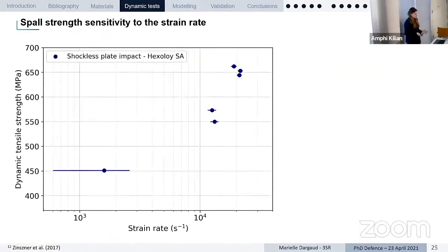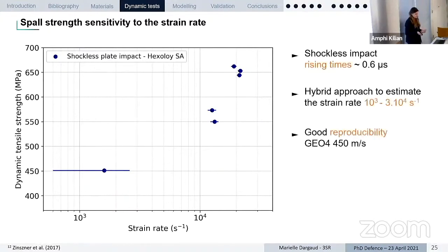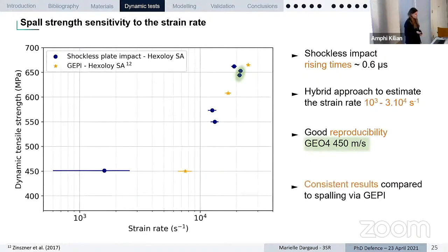From all these results, we can get to this plot where each point is just one single experiment. So here you have, for the material Hexoloy SA, the evolution of the dynamic strength according to the strain rate. You can see that we have a sensitivity to the strain rate. We can also see that for 2 tests in the exact same configuration, we get the same results. So good reproducibility. We've compared these results with experimental results obtained from the GEPI technique that are present in the literature on the exact same material. And we can see here that we have a good fit. We have something which is coherent between the 2 techniques.